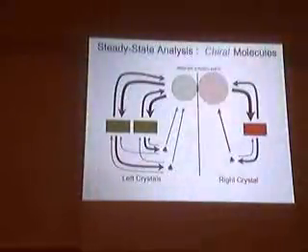And what you observe here is that once you enter the single solid state at the end, you will see that the concentration drops, isn't it? Yeah, sure. That's the same in our model. And the reason the concentration drops, in my model, is that at the end there are more crystals, so more ways of reincorporating, so slower dissolution. So the more the crystals accumulate, the slower they dissolve. The way we see that in our model is the last picture I showed you.